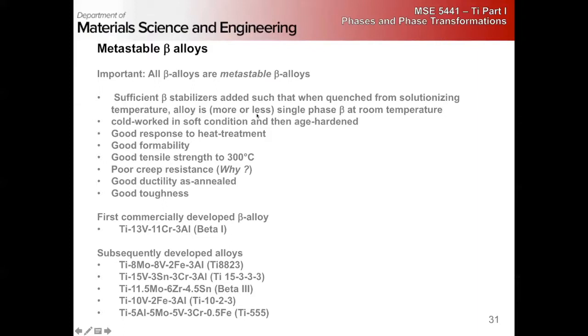Where the alloy is approximately single-phase beta at room temperature. The thing to note is that all beta alloys are really metastable, right? They're low enough that really the material wants to be alpha plus beta, right? And so the term beta alloy is a little confusing because a lot of authors will lump alpha plus beta alloys like Ti-6-4 in with beta. Others will separate out ones that are used only in nearly the beta condition.